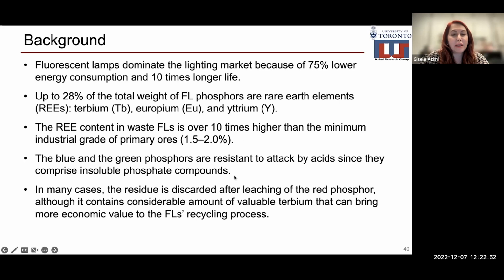Fluorescent lamps dominate the lighting market because of the 75% lower energy consumption and 10 times longer life. Up to 28% of the total weight of fluorescent lamp phosphors are rare earth elements, mainly terbium, europium, and yttrium. The rare earth content in waste fluorescent lamps is over 10 times higher than the minimum industrial grade for primary ores, which is 1.5 to 2 weight%.